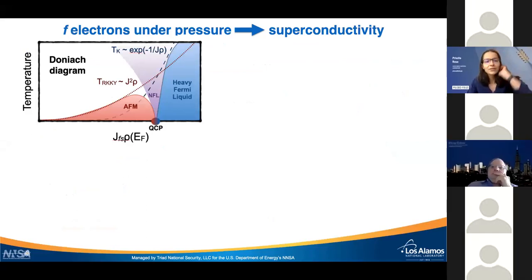On F-electrons under pressure, and in particular, the emergent phenomenon of superconductivity. And this can be really nicely seen in the so-called Doniach phase diagram. Here we have temperature versus the exchange coupling between F-electrons and conduction electrons times the density of states at the Fermi level. So at the very left of the diagram, we have an antiferromagnetically ordered state usually.